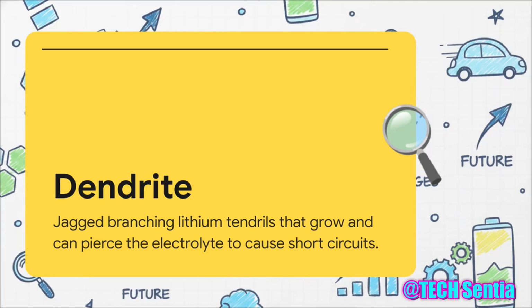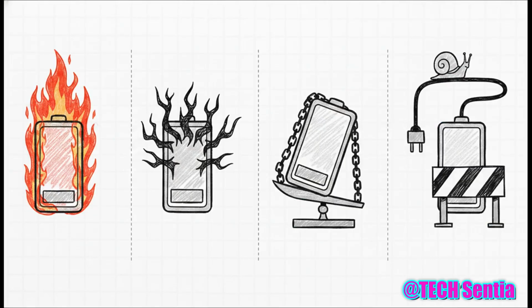But to get why that is so insanely difficult, we've got to talk about the bad guy of our story, the dendrite. Imagine a microscopic, jagged, unpredictable weed growing inside the battery. Every time you charge up, especially if you're trying to use high-power, pure lithium metal, these branching tendrils grow. In a liquid, they can stretch all the way across, pierce the middle, and touch the other side. And when that happens, bam, direct short circuit and potentially a really intense fire. These dendrites are the exact reason engineers have had to compromise for decades, settling for weaker graphite instead of pure lithium. So we're stuck with four fundamental limitations of liquid electrolytes that no amount of clever engineering can truly bypass.